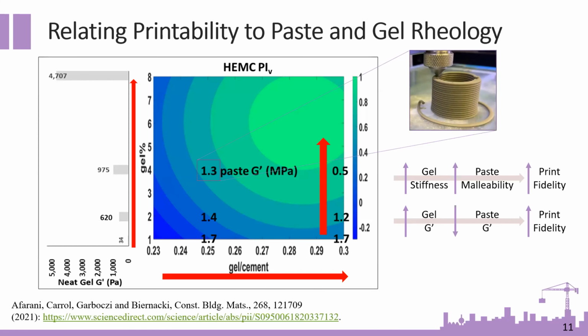Here in this graph, which is a complex graph, we superimpose the rheological information of the gels on the left side of the graph and the paste storage modulus inside of the graph. As you can clearly see, as we increase the gel concentration, the gel storage modulus increased, and the printability improved. Whereas as we increase the gel concentration, the paste storage modulus decreased, and also the printability improved.